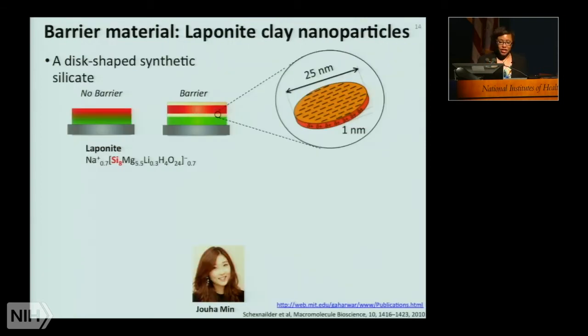So now we want to introduce an anti-infective. And the way that we do this is by introducing gentamicin sulfate. Turns out to be another charged drug molecule. And here my student Jouha Min came into the picture. She began to first model these systems and their release characteristics and then to build them. Here she's using red to demonstrate the gentamicin sulfate and green to represent the BMP2. And she quickly began to construct material systems in which there was no barrier and you could get some degree of stagger. But she also introduced barrier layers by using naturally occurring laponite clay.